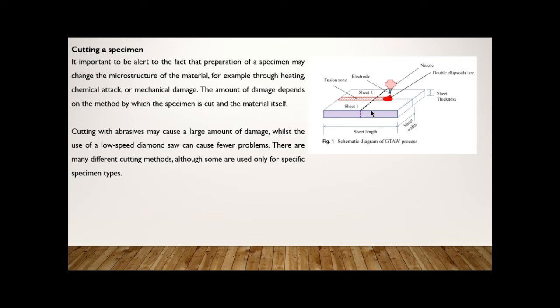The expected results may be deviated due to this extra heat input. I request you to use wire cut EDM if you have metal samples or conducting materials. Otherwise you should go for water jet cutting. Abrasive wheel cutting I will never say, but you can go with disc cutting. It is also suitable for most of the aluminum and other specimens. If you have titanium or Inconel, go for wire cut EDM.